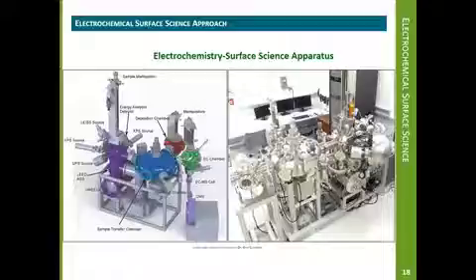Located in our labs is a purpose-built, custom-designed, tandem electrochemistry surface science apparatus. Housed within the ultra-high vacuum analytical chamber of this apparatus are a number of surface analytical techniques, including X-ray photoelectron spectroscopy, low-energy ion scattering spectroscopy, temperature-programmed desorption, Auger electron spectroscopy, low-energy electron diffraction, and high-resolution electron energy loss spectroscopy. In this apparatus, a hermetically sealed vacuum chamber has been designed to accept an electrochemical cell. This electrochemistry chamber is attached to a gate valve isolable central distribution chamber, which is interfaced with a surface analytical chamber and a thin film deposition and surface process chamber with mechanical transfer mechanisms designed to perform sample handoff between chambers.